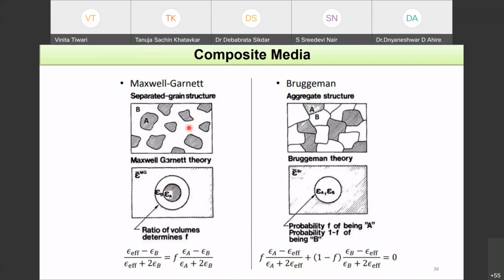And there, if you consider the volume fraction that is populated by the nanoparticles as F, you can calculate the effective refractive index or effective permittivity of this mixed structure. The Bruggeman configuration does something very similar, but in this case you have an aggregate structure. So you do not have a very separated grain structure like Maxwell-Garnett. Here, in the effective medium theory, you can get the permittivity by assuming that F is the probability of that particular material being A, and 1 minus F is the probability of that material being B. So if you take that into consideration, this equation gives you epsilon effective, which is the effective permittivity of this kind of structure.